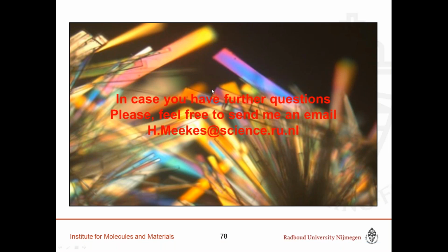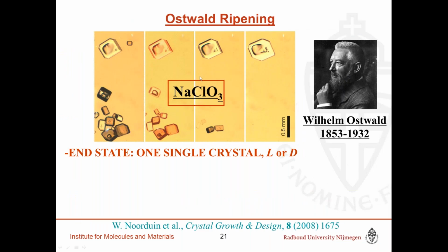Yes, that's a very good point. And for that, I would like to go back to one of my slides, where you see exactly what is the matter. If you have a slurry like this, even if you don't move it at all, you don't change temperature, then this is not the thermodynamically stable state. That is because of the high energy in the interface between crystal and solution.